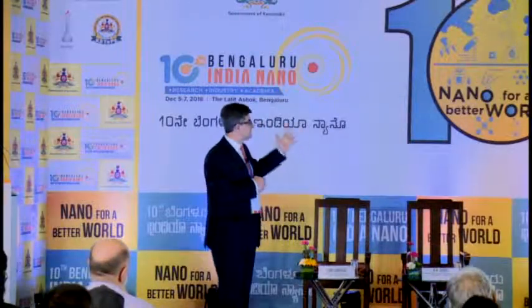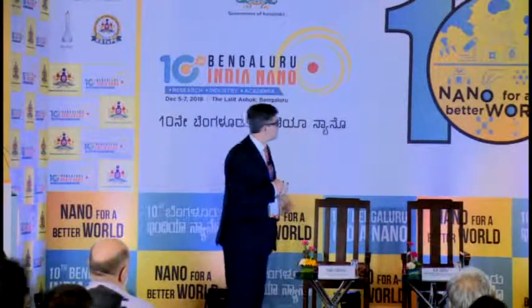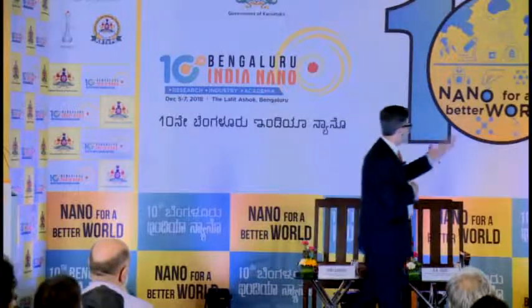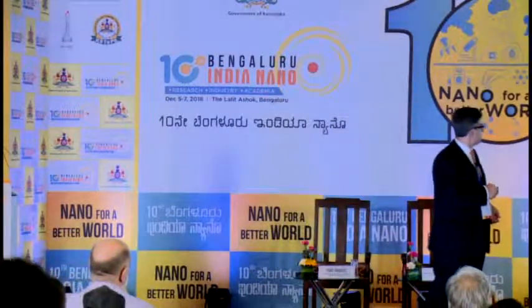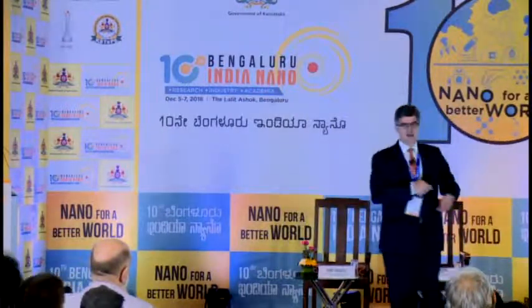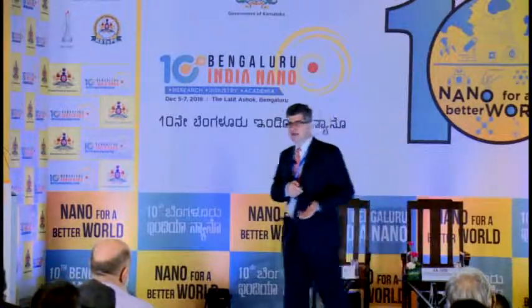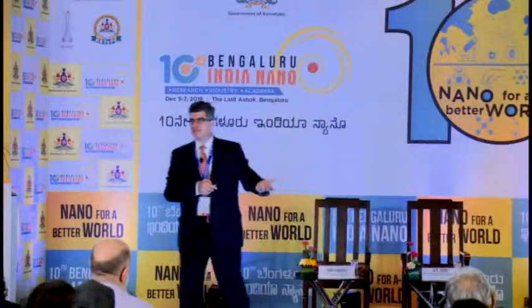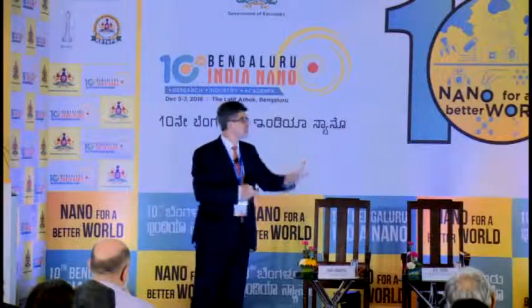So the process is very simple. We take a powder, we dump it into solution. We get it etched, and we produce, and this is like a 1 liter bottle with about 400 milliliter colloidal solution, 10, 20 milligram per milliliter of single layer particles.